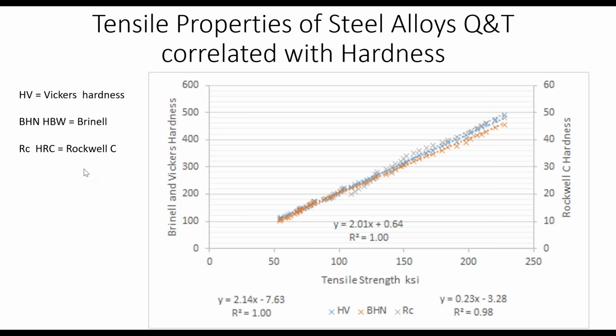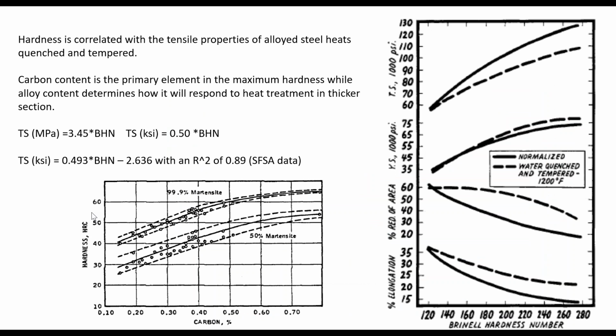And in steel castings, we've always preferred Brinell hardness because our microstructure is coarse and large, and so you get lots of variation if you use Vickers hardness or Rockwell C. You have to take lots of measurements and average them. And Brinell hardness with a 10 millimeter ball averages it with the measurement itself. So we prefer Brinell hardness in steel casting technology.